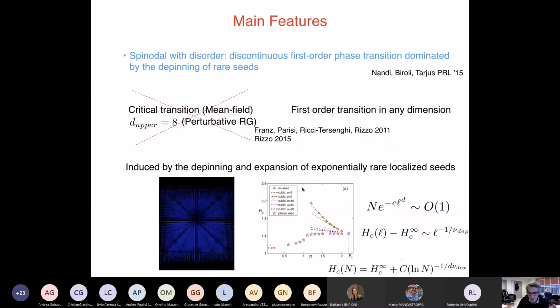So here, for example, the green points are no seed. The green line that you have here is a seed of size 3. And since the two are together, this means that for the size that we used, we had seeds of size 3 inside the system. Instead, when we put the seed of size 5, we find this value of HC, which is lower, which means that given the system size that we used in simulation, we didn't have seeds of size 5.